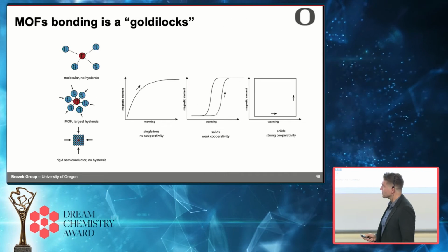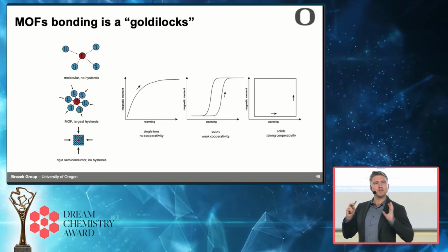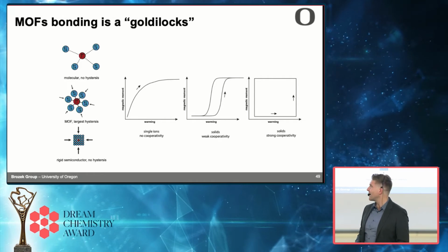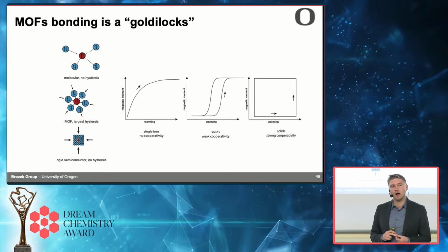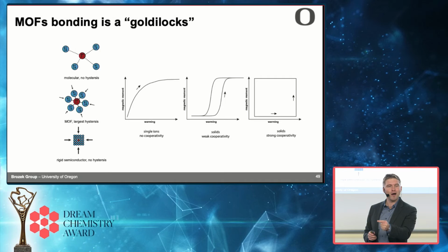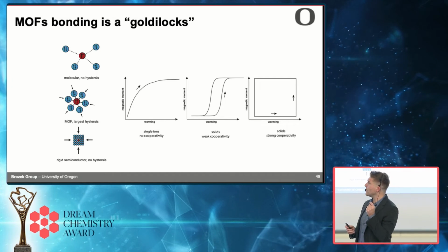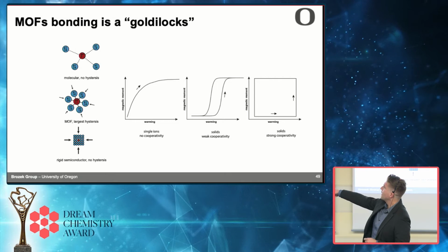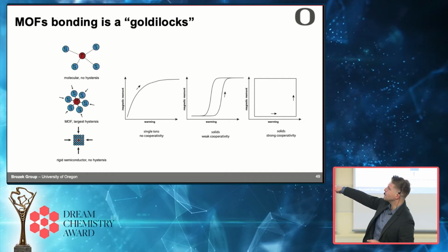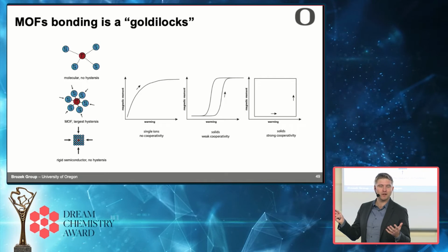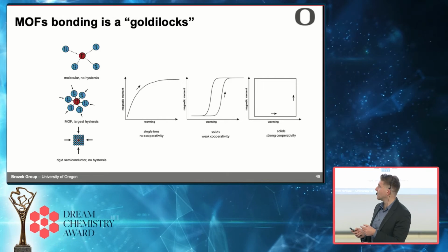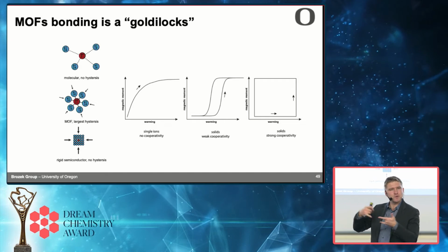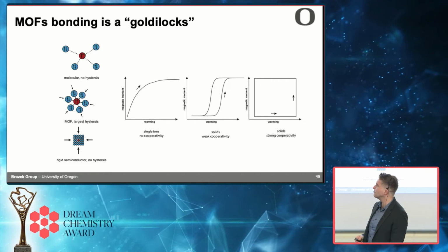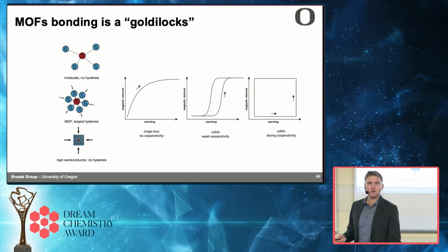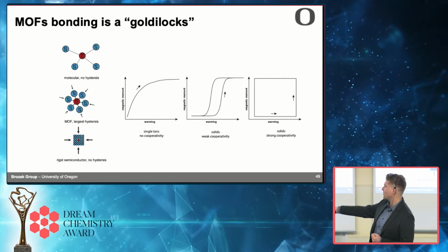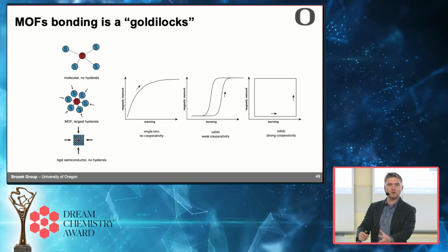Well, here's my proposal. The reason that iron triazolate has such a wide hysteresis window and such sharp transitions and so much cooperativity is because I think MOF bonding is sitting in this perfect Goldilocks regime where the bonding isn't too weak and it's not too strong. If you have a molecular crystal that undergoes spin crossover, if one of those molecules goes high spin, the neighboring molecules don't care because they're not bound to each other. In fact, the only molecules that show a hysteresis are where in the crystal structure there's hydrogen bonding or some sort of weak bonding where they influence each other. Most conventional solids don't show spin crossover because the bonding is too dense, too strong. If a magnetic center goes high spin, the surrounding lattice just pushes it back into the low spin.